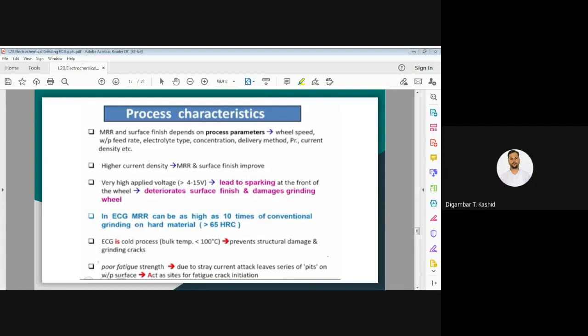If it goes beyond that, then there is structural damage and grinding cracks may generate. Due to that, poor fatigue strength may be observed in the electrochemically ground workpiece, because stray current may occur by this grinding wheel. Because of stray current, small pits are generated on your machined surface. That current attack leaves a series of pits on your workpiece surface, so it acts as sites for fatigue crack initiation.